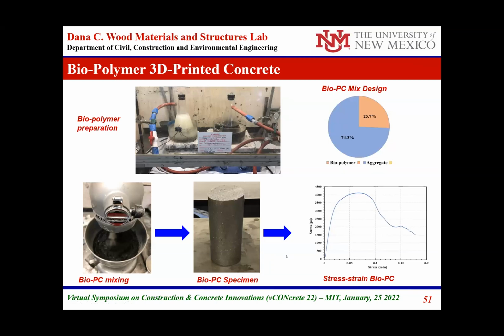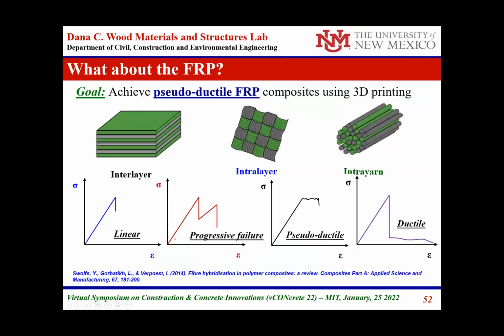Related to CO2, and that, of course, was polymer concrete. That's also an issue. So what we are trying to do is develop a biopolymer that is polyurethane-based, and we use this polyurethane polymer to mix concrete and develop concrete specimens. That's the stress strain of it, and you can see that we can develop a 4,000 PSI concrete. The work we are doing today is taking this to be 3D printable, where this is definitely a much lower carbon footprint material than the typical material.